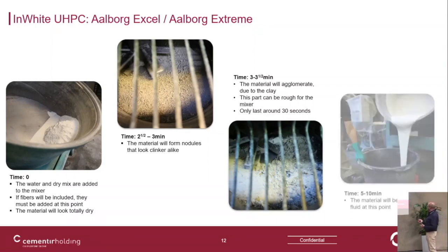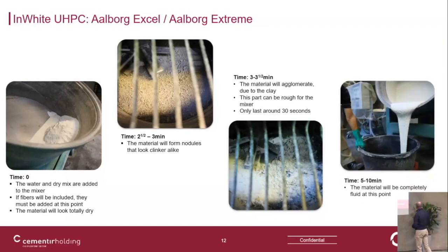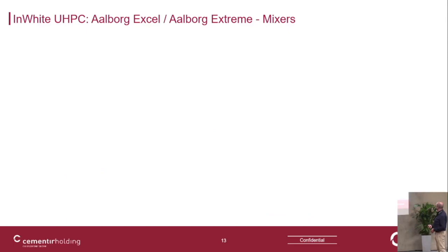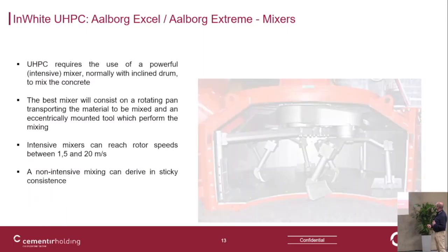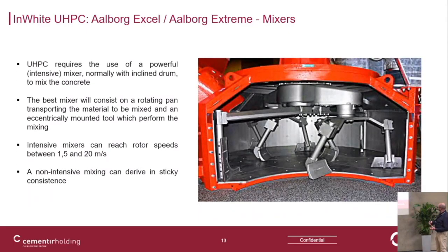And then going up to 5-10 minutes, we arrive at the final consistency, and this is a very flowable mix with a spread with a cone of about 90 centimeters with the big cone. But we do also some tests with American standards, and this is with a smaller quantity of mortar where we have the spread of around 29 centimeters.